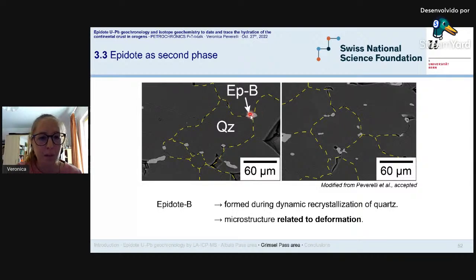If epidote precipitated here, then it means that epidote precipitated after the beginning of deformation. At the same time, I told you that epidote controls how large quartz can grow during dynamic recrystallization. So epidote must have precipitated here before the end of deformation. So in other words, this microstructure formed during deformation and epidote B crystallized during deformation.